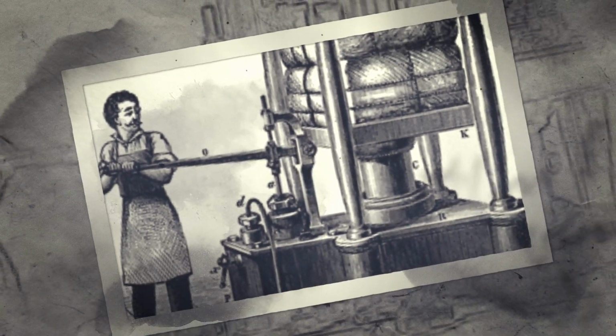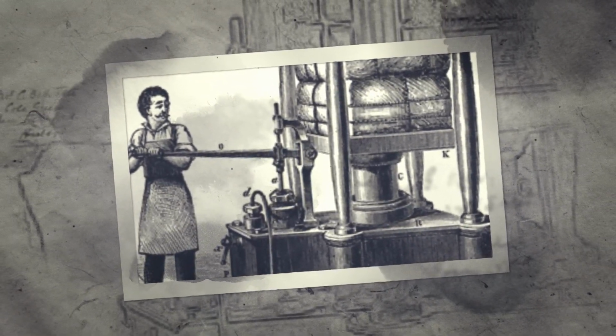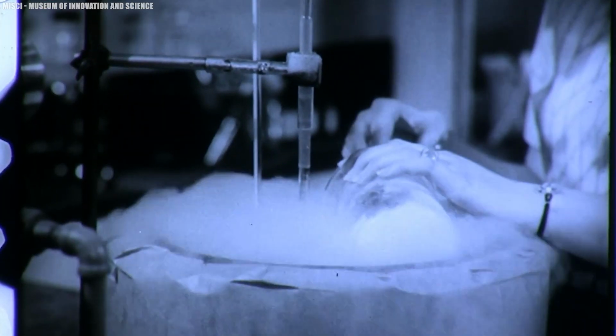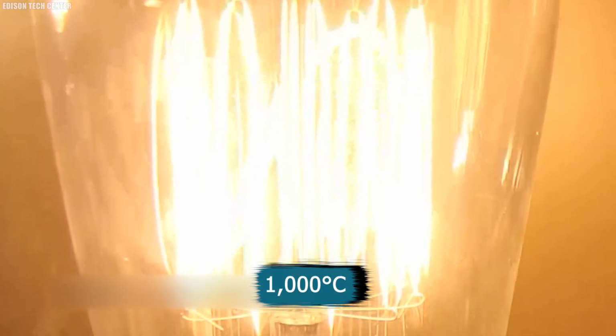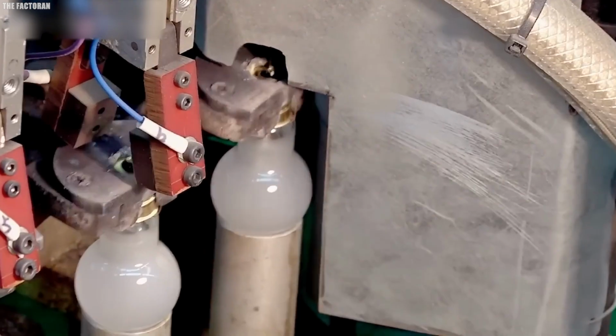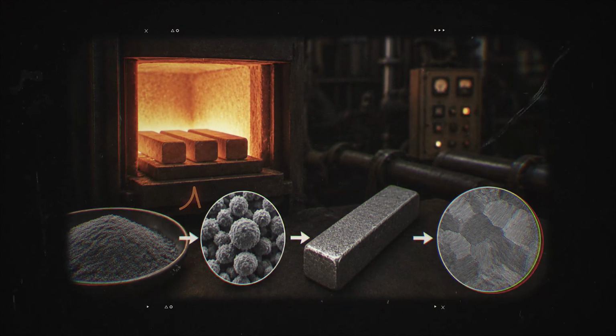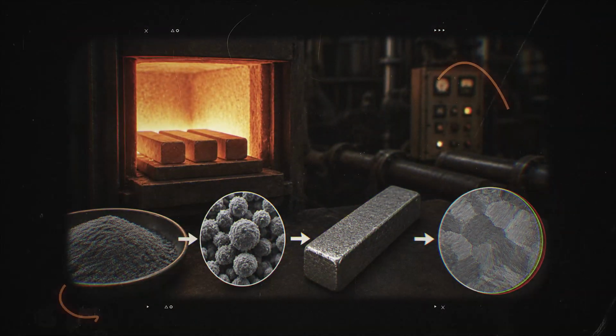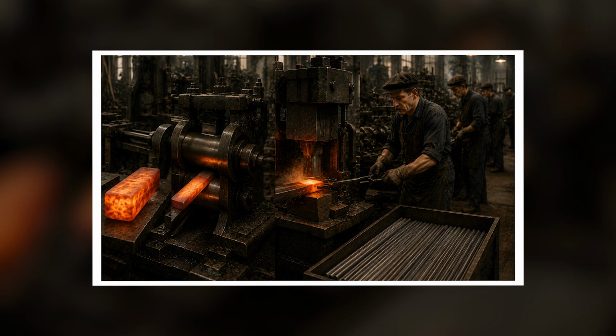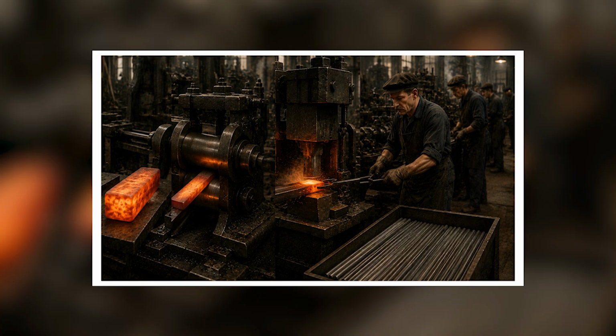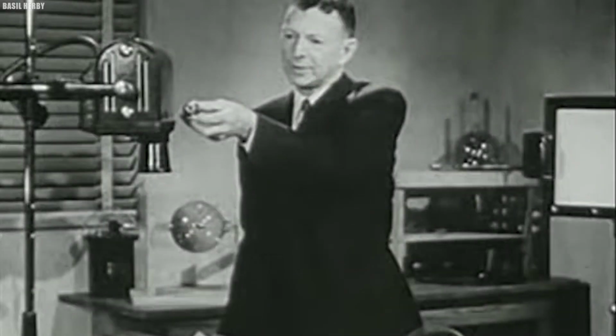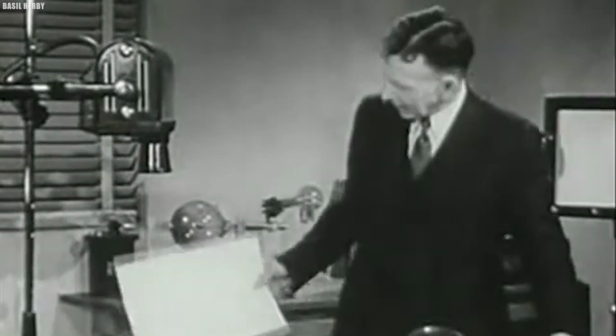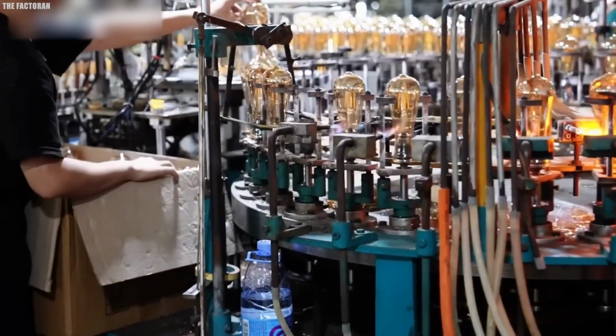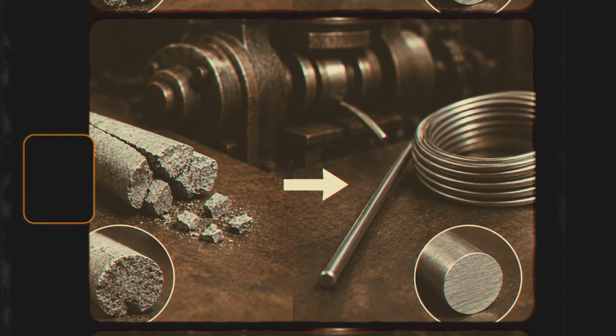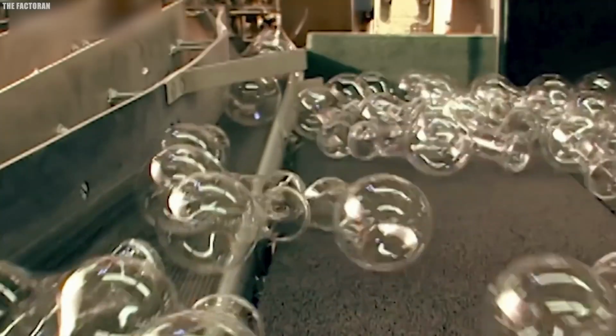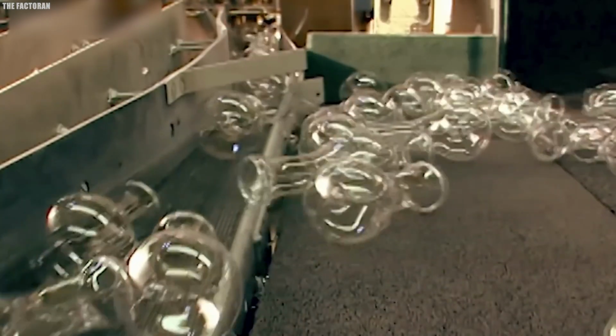Purified tungsten powder was first pressed into rectangular bars using hydraulic presses, then sintered in hydrogen atmosphere furnaces at temperatures exceeding 1,000 degrees Celsius, a process that fused the powder particles into a solid, coherent mass without fully melting the metal. The sintered bars were then worked mechanically through a sequence of swaging and forging operations, progressively reducing the cross-section while improving the internal grain structure of the metal. This mechanical working was what made Coolidge's process distinct. It transformed inherently brittle sintered tungsten into a material capable of further reduction without fracturing.